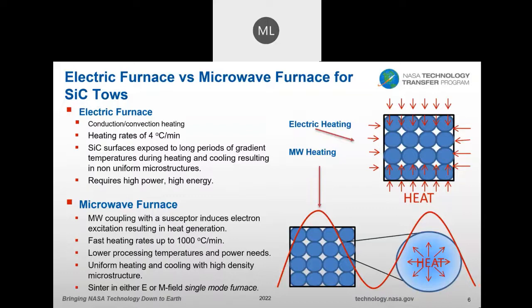In the case of the microwave furnace, microwaves couple with the susceptor, inducing electron excitation, resulting in heat generation. It has very fast heating rates, up to 1,000 degrees per minute, has lower processing temperatures and power needs, and you can get a uniform microstructure because of the rapid heating and the rapid cooling, so you're not having excessive grain growth within your microstructure. And in this case, we can sinter in either the magnetic or electric field, as I mentioned before. Next slide.